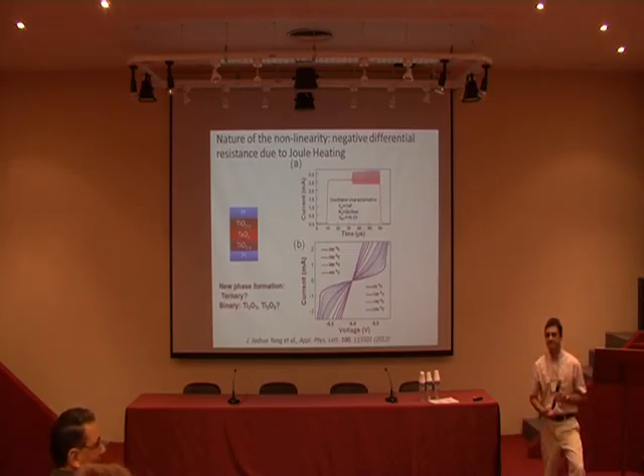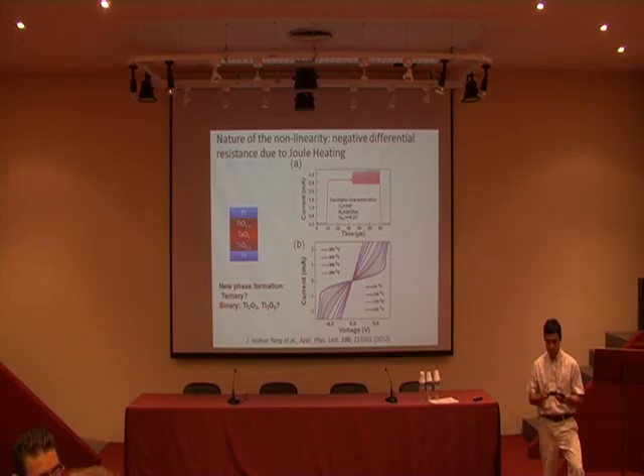But do you have to have a phase transition for thermal breakdown to occur? I certainly sense that in vanadium oxide that's happening, there is a phase transition. But the theory of thermal breakdown was originally developed decades ago, for activated systems. So you can have thermal breakdown if you just have an exponential dependence on the temperature. You don't need to have a whole phase transition.